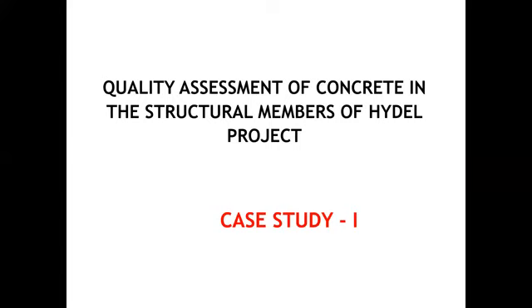So vibration studies were done. Ultrasonic pulse velocity, rebound hammer, and chemical tests were done. This is UPV and chloride. All that has been done. Now, as far as the columns are concerned, the UPV values are very good. Absolutely, there was no issue. Sulfates are well within the limit. The pH value was good. Chlorides are very well within the limits. Absolutely not a problem. The whole issue was, the UPV test clearly indicated that the 8 concrete pedestals supporting the starter and support pad gave a lot of unstable readings in the UPV values, which shows very clearly the grouting of the bolt pockets in the pedestal was not done properly, and that resulted in this excessive vibration and resulted in failure.